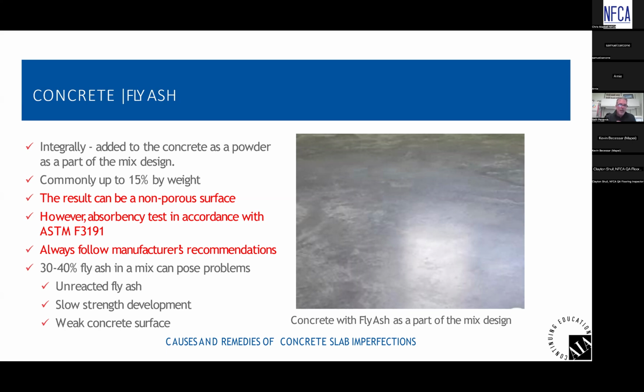A couple of things can happen when we have too much fly ash in concrete. You get into levels like 30 and 40%. You could have unreactive fly ash in the concrete because there's not enough free lime in there for the chemistry to happen. It could equate to very slow strength development, and it could also equate to a weak surface. So again, not that I expect you, or should any of us, be able to identify fly ash in concrete just by doing a visual, but get out there on the concrete and evaluate it, scratch it, cut it, do some absorbency tests so you know what we're dealing with from an absorbency standpoint and an integrity standpoint, and you raise the red flag as necessary.